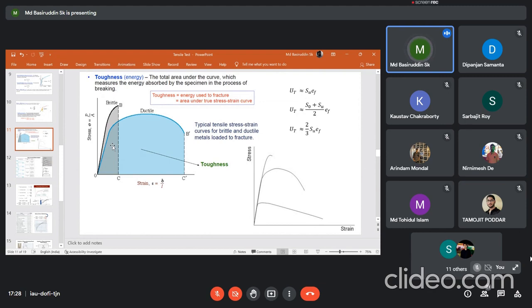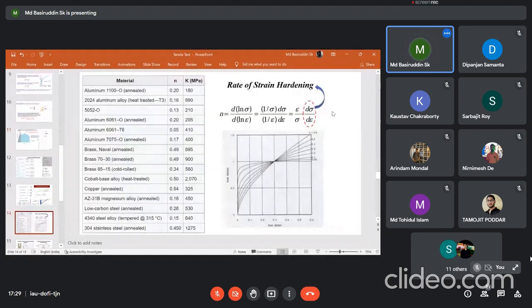Now, when a lot of defects come, they will interact and impede the movement of other defects. That is why from YS to UTS you will find that gradually the load requirement for deformation increases. As the dislocations interact with each other and impede the motion of other dislocations that assist the slip, you need to overcome those barriers. You have to apply more and more load till the UTS. In other words, the rate at which the material experiences this resistance can be measured by the rate of strain hardening, that is d sigma by d epsilon.